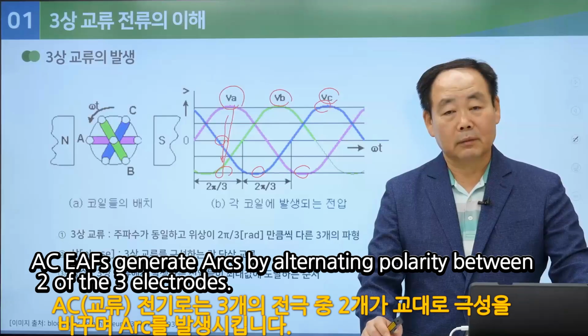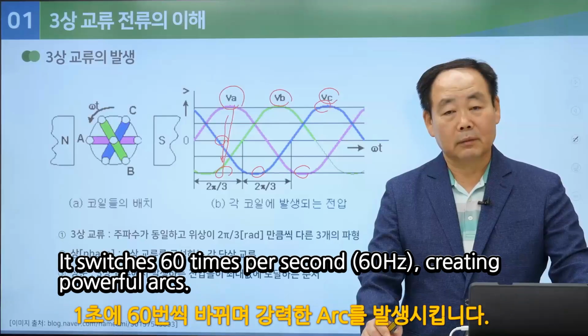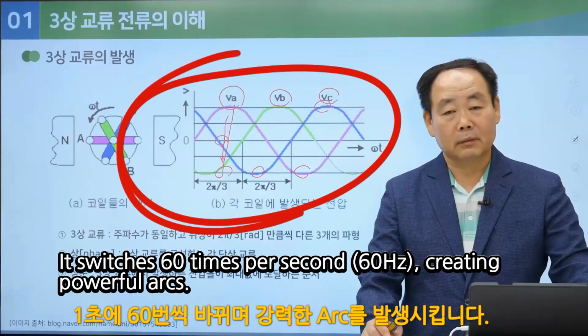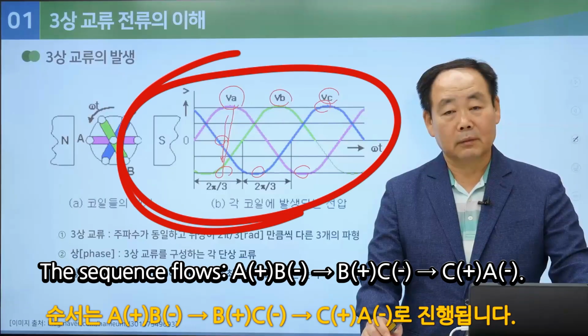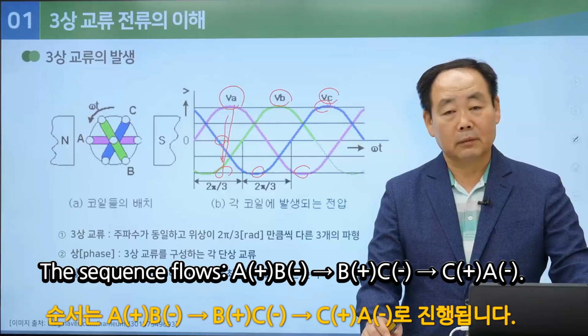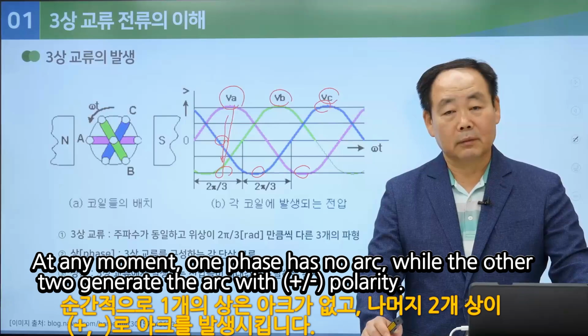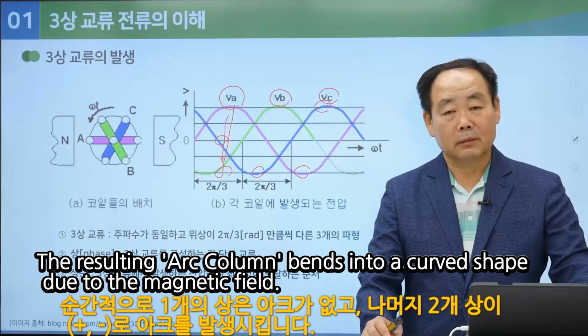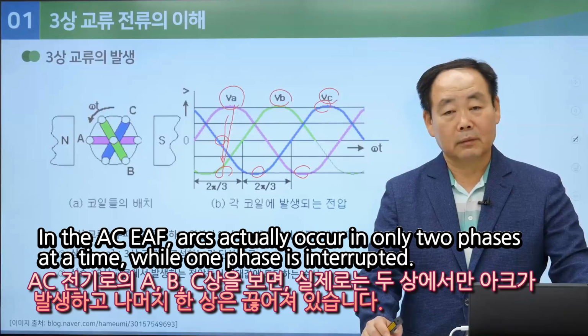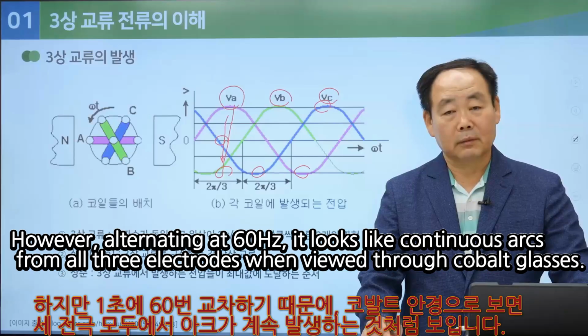AC EAFs generate arcs by alternating polarity between 2 of the 3 electrodes. It switches 60 times per second, 60 Hz, creating powerful arcs. The sequence flows A plus B, B plus C, C plus A. At any moment, one phase has no arc, while the other 2 generate the arc with plus or minus polarity. The resulting arc column bends into a curved shape due to the magnetic field. In the AC EAF, arcs actually occur in only 2 phases at a time, while one phase is interrupted. However, alternating at 60 Hz, it looks like continuous arcs.